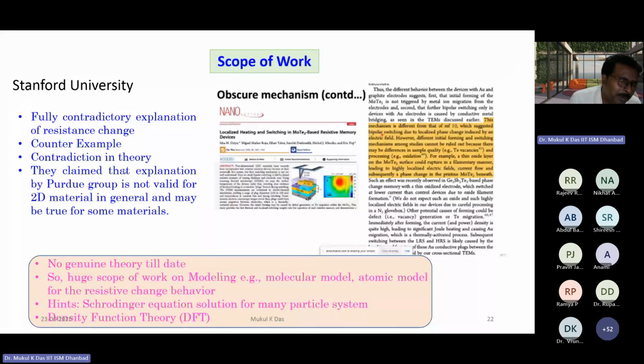But when a metal migrates from the electrode to the MoS2, some energy states are created in this gap. Due to the creation of energy states, there is a possibility of carrier flow, that is, existence of carriers in these gap states. That is the basic theory proposed by this group of people, and also by a renowned scientist, Professor Santanu Mahapatra at IISc Bangalore in India. In that molecular theory, they have shown that migration of metal into the 2D material is the origin of the change in the memristor or resistive memory.